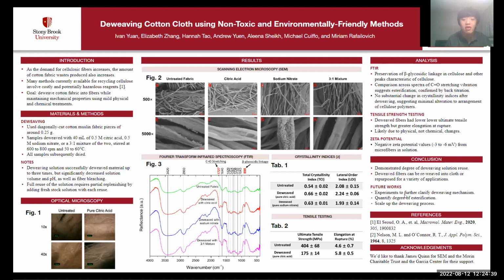Comparison across the spectra of the C=O peak suggests that esterification between citric acid and cellulose occurred, which we later confirmed through back titration. The FTIR data was also used to compute crystallinity indices, shown in table 1, which have no substantial changes after deweaving, suggesting minimal alteration to cellulose polymer arrangement.